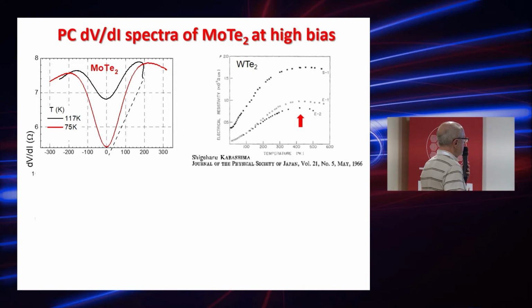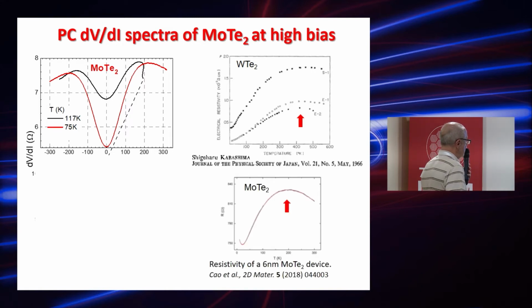Such behavior for bulk samples of molybdenum ditelluride was not known, but there is such behavior for thin film of molybdenum ditelluride. It means that in point contact we see similar behavior to the temperature dependence of resistivity. So in principle, this differential resistance of point contact is similar to the dependence of resistivity versus temperature.